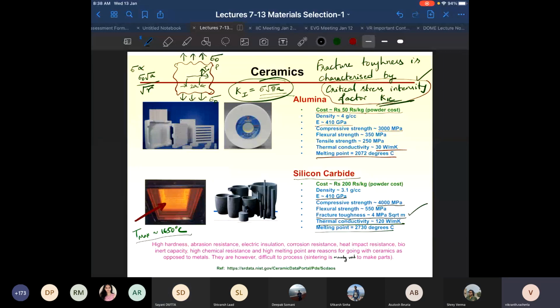So the high thermal conductivity materials are much better at maintaining thermal equilibrium, or much better in diffusing the heat and reducing the thermal gradients which occur within the system. That is precisely the reason why you would prefer a copper bottomed vessel for cooking as compared to a stainless steel vessel. It can reduce the thermal gradients within the system. So high thermal conductivity and consequently high thermal diffusivity of silicon carbide, along with moderate fracture toughness, makes it a very good candidate for heating elements. Okay, so it is used in furnaces.